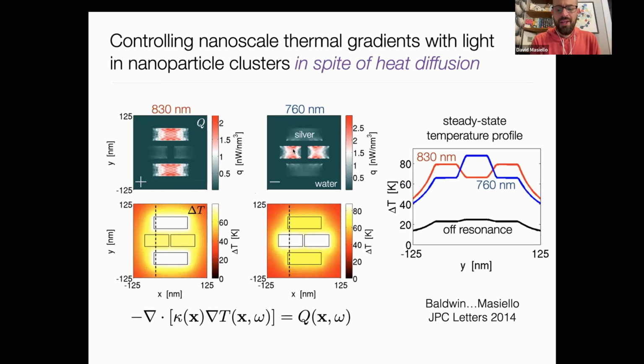And okay, fine. Then we thought, well, certainly if we solve the heat diffusion equation in steady state, it would never be that the temperature would be any different on any of the four particles. We thought it would always be the same. But in fact, we were wrong. So numerically solving in steady state the heat diffusion equation led to a temperature profile for the in-phase mode that actually preferentially was hotter on the outer two rods than the inner two rods, and vice versa at the other linear combination, the other way around happened. This was really quite surprising to us.